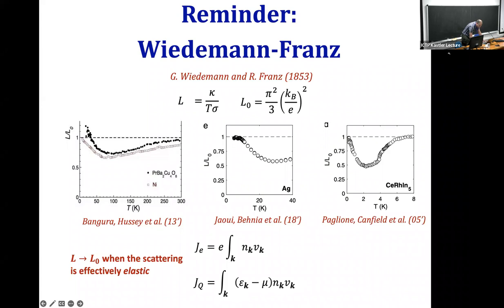So what happens here is that this is a heavy fermion compound, okay, and at high temperature you have quasi-elastic scattering from the local magnetic moments. This is the reason for this recovery. Okay, so it's actually quite different physics, but it's not phonons here.